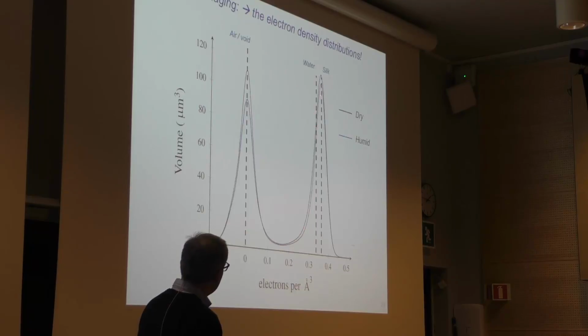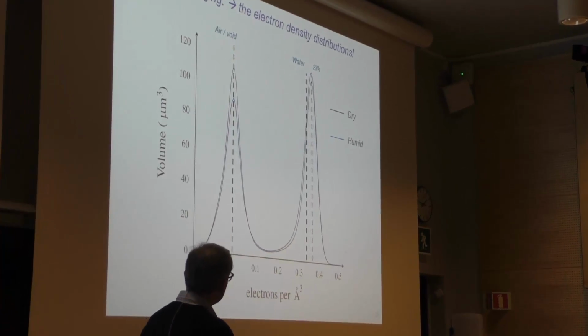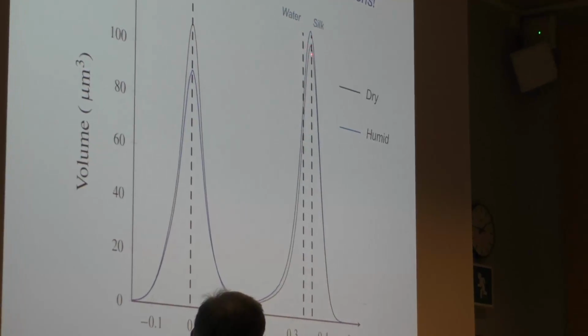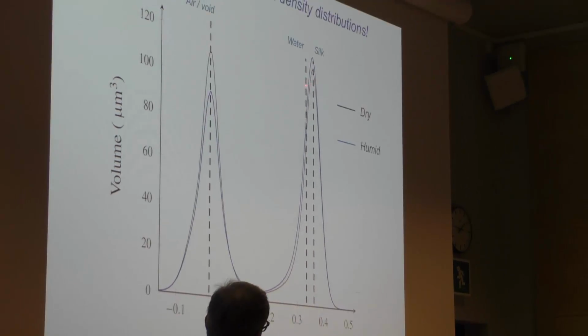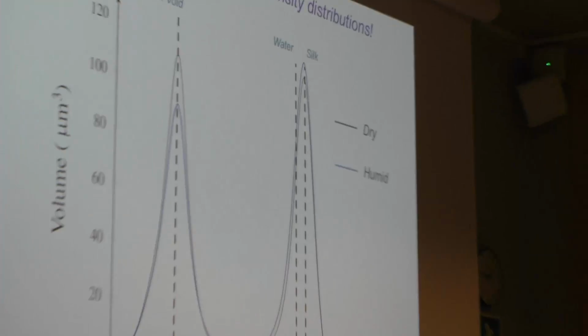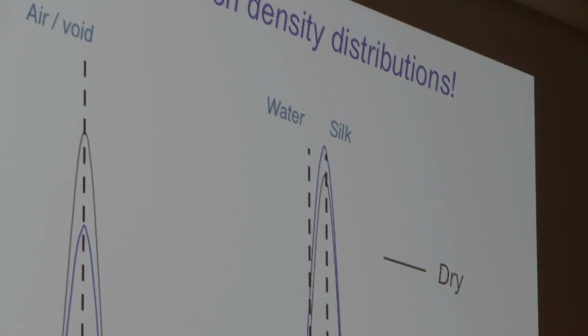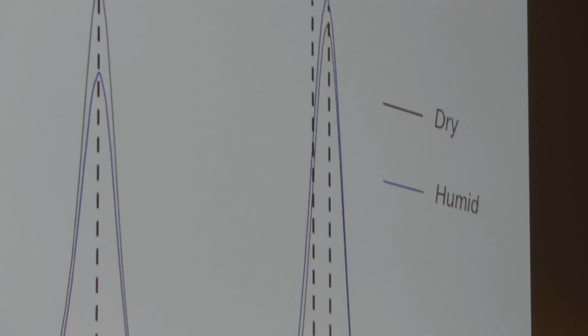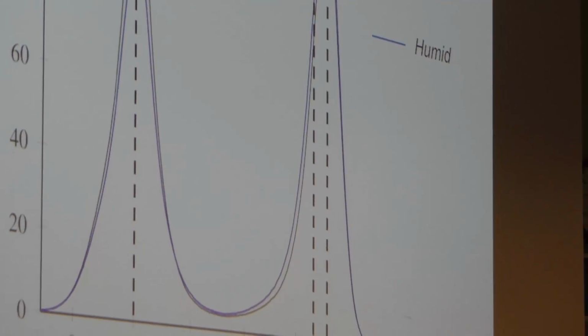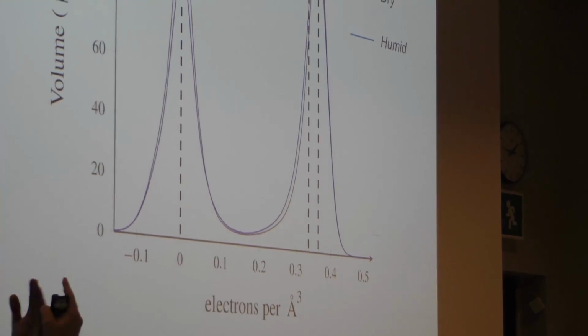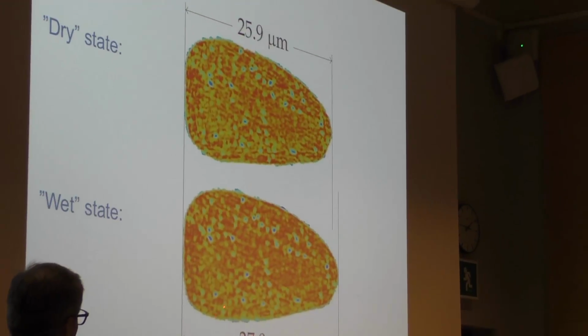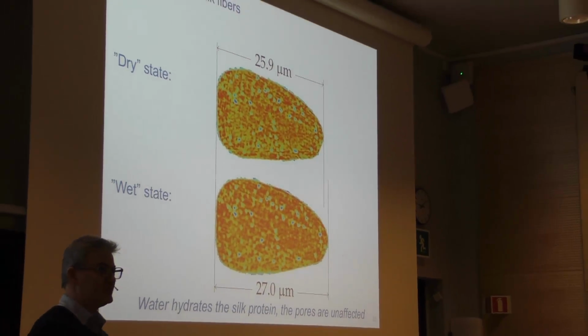Basically, the black one is the before, in the dry state, the blue one is in the wet state, and you can see that the number of voxels containing air goes down, of course, because the silk fiber swells, and you can see that here the difference in electron density between water and silk is very low. So if the water had gone into the pores, as I said, these would have appeared reddish afterwards, right?